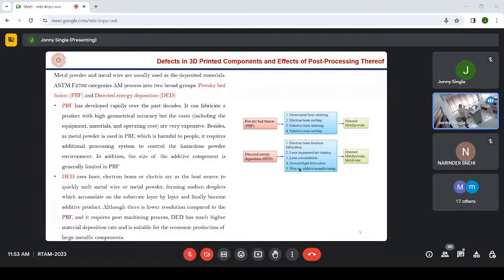The second is directed energy deposition. This uses laser, electron beam or electric arc as the heat source to quickly melt metal wire or metal powder, forming molten droplets which accumulate on the substrate layer by layer and finally become the additive product. Although there is lower resolution compared to PBF, that means the quality of the product is not as high as we get in PBF, and it requires a post machining process also.